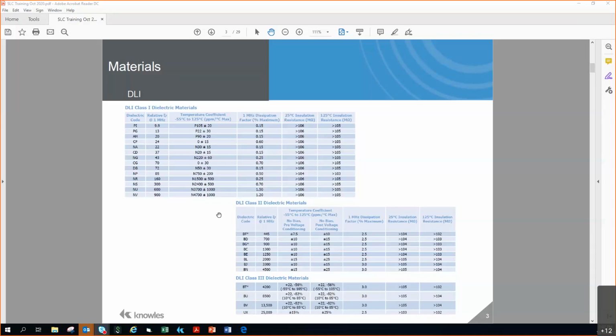You're not really losing anything from a TC, a temperature coefficient. As you can see, the UX is a 25,000 dielectric, but we're also still in an X7R material. You still have a good dissipation factor at 2.5, and your insulation resistance is still high. Not as high as the other ones, but it does do a good job. Anybody have any questions on the materials?